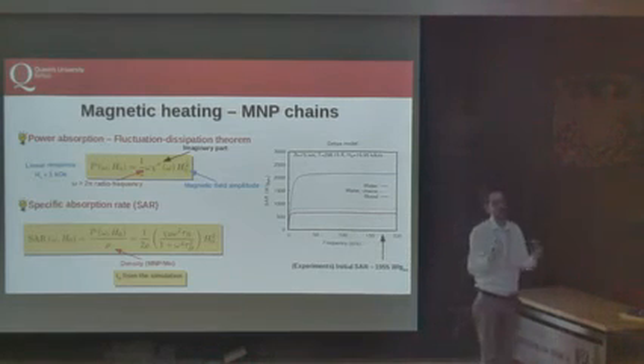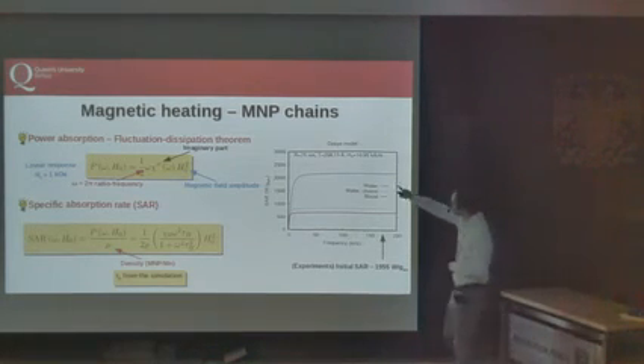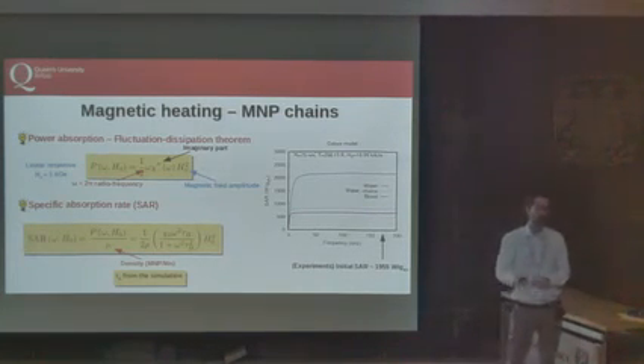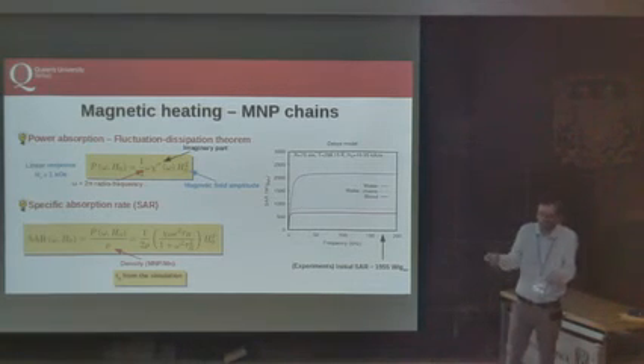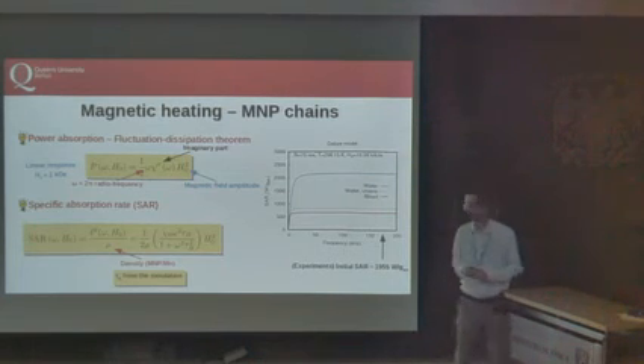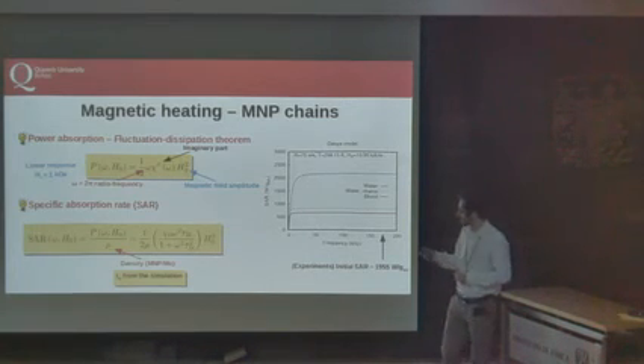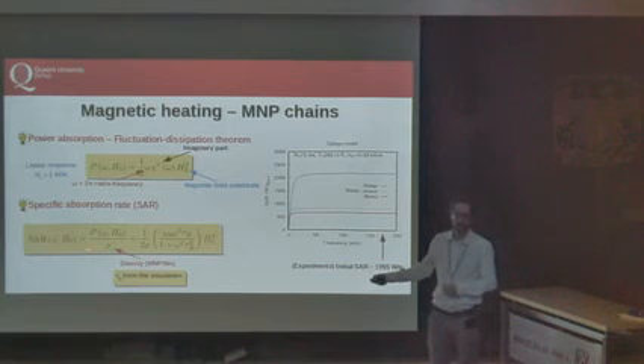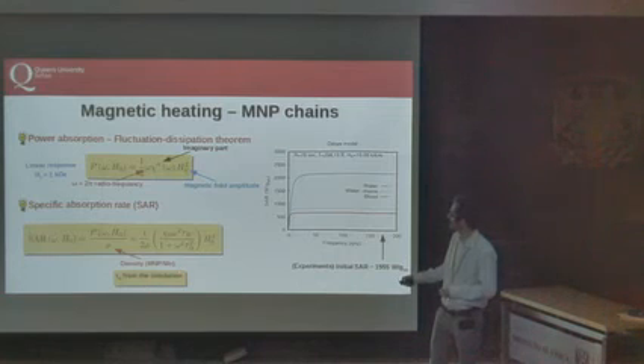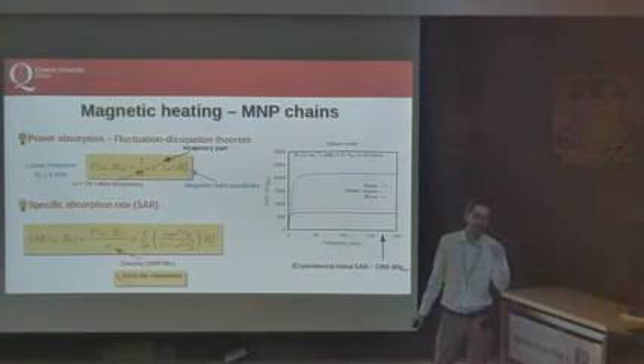The effect on the SAR, of course, is to reduce the SAR. If there are chained solutions, the SAR is much reduced and is approaching the value of blood, which means that probably the effective viscosity that one can use to describe this fluid is very close to the viscosity of blood, which is roughly 3 times the viscosity of water. So we use the exact theory for single nanoparticles, but we applied the Brownian time obtained from the simulations.